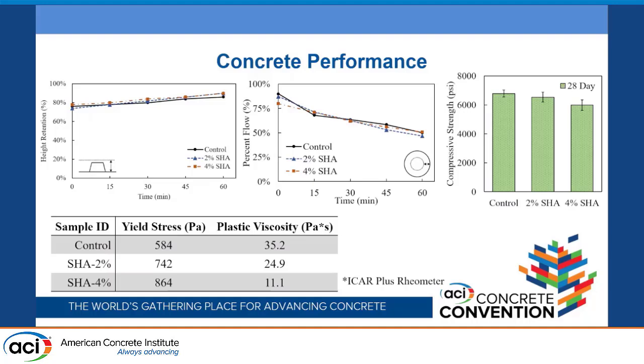For rheological performance, we first and foremost started with testing using the flow table, where we did a height retention test, which is pretty simply molding your sample, and then before dropping the table, you demold the flow table, and you measure the change in height caused by self-weight. Typically, you want to see approximately an 80% retention.